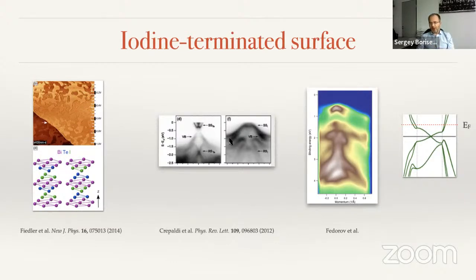But actually, considering the valence band spectra, we have a feeling that the iodine terminated surface corresponds just to the shift of the band structure towards the Fermi level, meaning the Fermi level is much closer to the 3D Dirac point. Therefore, the suggestion would be to stabilize somehow the iodine terminated surface of the single crystal, and this could give the way to get a stable material with a canonical 3D Dirac point at the Fermi surface.